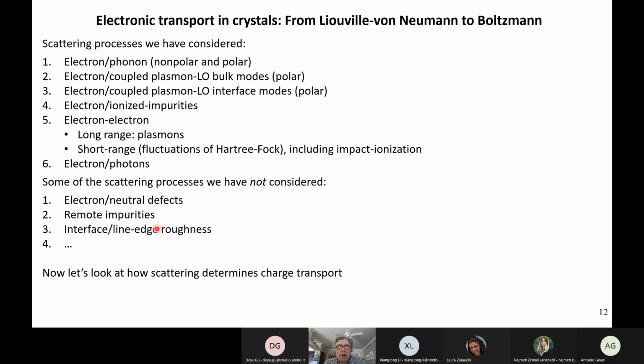But thinning the body or making a narrow section nanowire increases the likelihood that your surface will be far from ideal. There will be vacancies, protrusions, diffusion of other atoms at the interface, which will roughen the interface. Talking about nanoribbons, you may have instead the edges, which are roughened, so it's line edge roughness. The interface roughness is actually what is controlling, limiting, if you wish, the transport properties of thin silicon layers. And that's why people are looking at alternatives, such as two-dimensional materials.